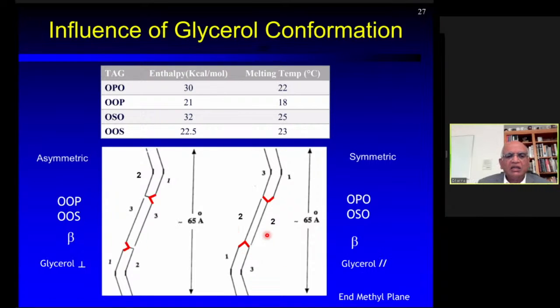So when we look at both these pairs of compounds, everything else is exactly the same. They pack in a beta substructure. The only thing that differs is the glycerol conformation. How this reflects in the physical properties of these materials is shown on the top. If we take the OPO and OOP, the symmetric compound has higher enthalpy and higher melting temperature, whereas the asymmetric compound has a lower enthalpy and lower melting temperature. That shows that when the glycerol conformation is perpendicular, it is a higher energy state than the glycerol which is parallel.